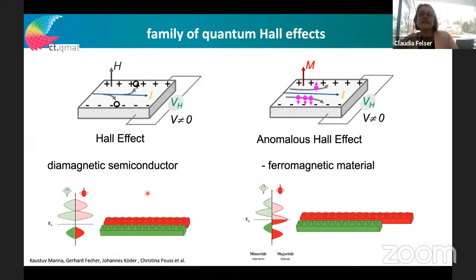So then we investigated the transport properties, and we do Hall measurements for this. As I said, we use a single crystal, put a contact on the single crystal, and then we measure the resistivity in a magnetic field in a Hall setup. And this we do normally for all our normal topological semiconductors. In case of magnetic material, we have this intrinsic magnetism, so we measure an additional contribution to the Hall effect, and this is the anomalous Hall effect. So this is what I show you in the following slide.